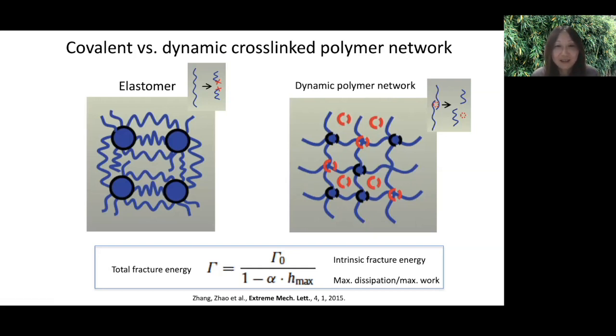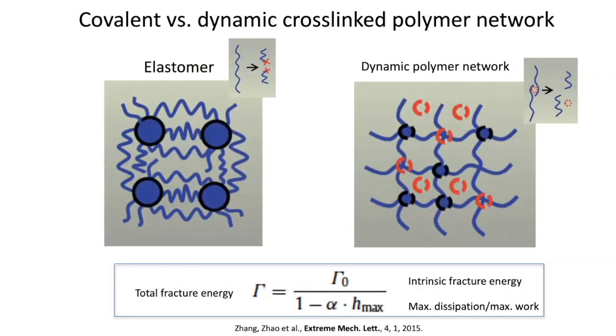And self-healing materials in recent years is the incorporation of dynamic crosslinks into polymer networks instead of the covalent linkages in conventional elastomers. The breakage of covalent bonds due to large strain will result in cracks and irreversible damage to the film. On the other hand, breaking dynamic bond is a mechanism for energy dissipation.